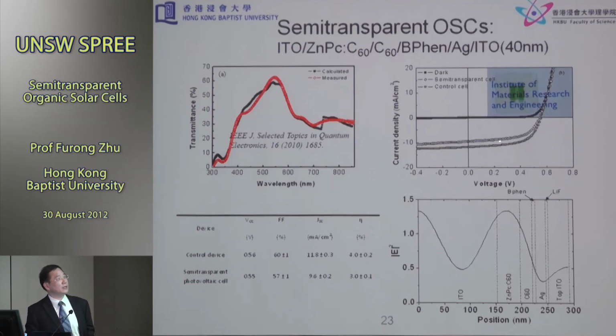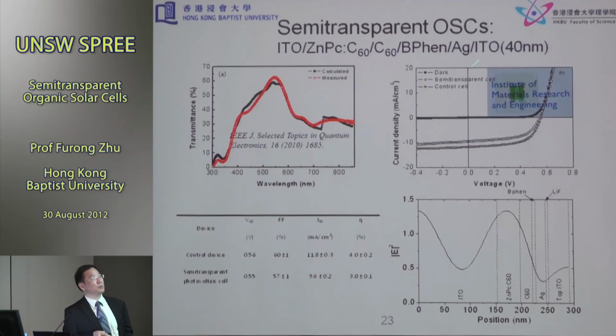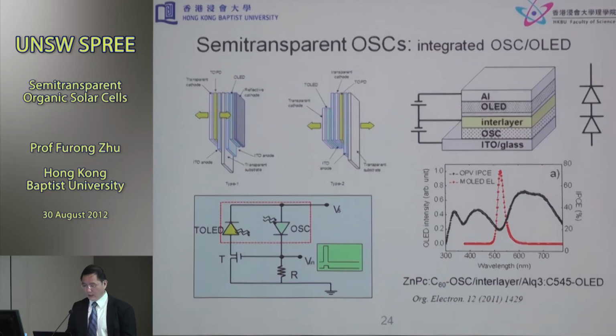So this is the opaque device, and when you replace it with a transparent ITO device, you get this efficiency. This is a control device with aluminum at 4%, and when you replace the aluminum with ITO, you get about 3%. So it's a very good agreement with the theoretical simulation. Essentially, this technique is very useful. You can apply it to other systems as well. Depending on the system and the blend layer you use, you probably need to tune the optimum levels, but once you know the technique, it becomes very easy. Otherwise, experimentally, you have to try and error.